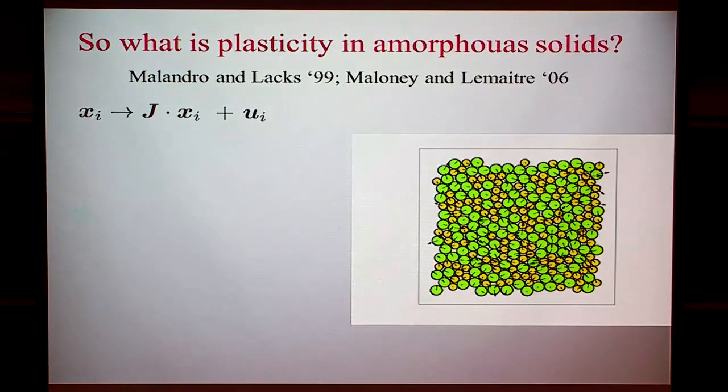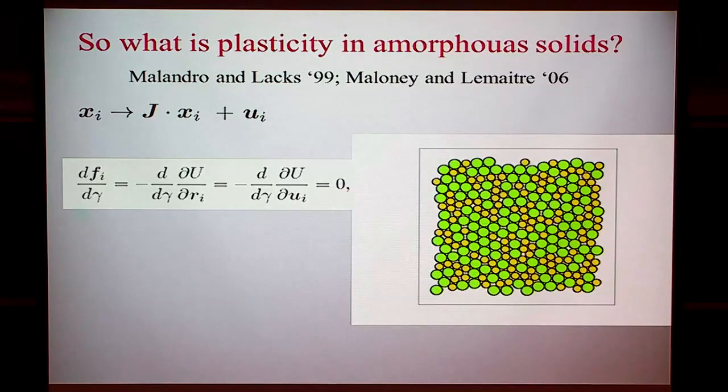These are now the forces, and now this is the non-affine displacement that's brought it back to a mechanical equilibrium, in the sense that the net force on every particle is 0. So now we can do a little bit of analytics. The force Fi on every particle was 0 before, and I'm going to now parameterize the affine transformation by some gamma. So for example, in this case, x goes to x plus gamma y, and y goes to y. So the gamma will just tell you how much I'm going to shear.